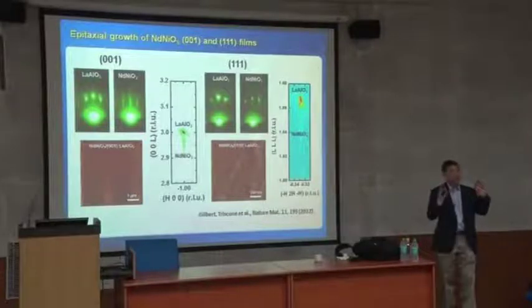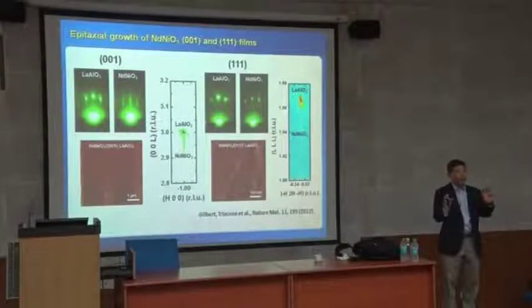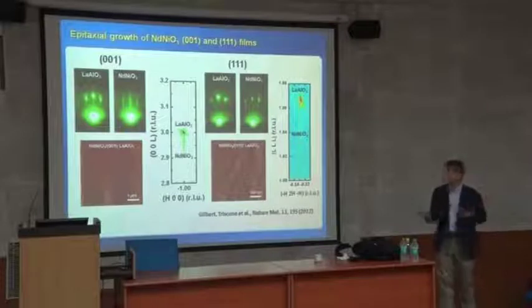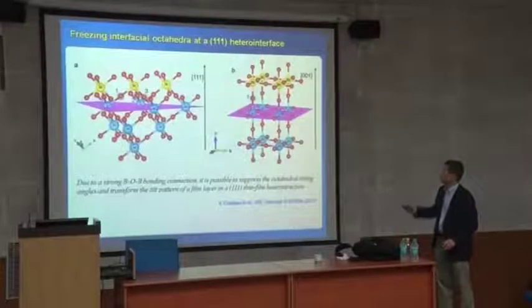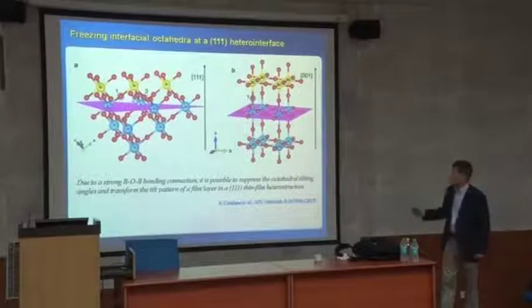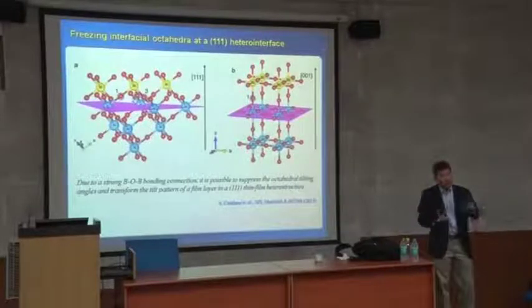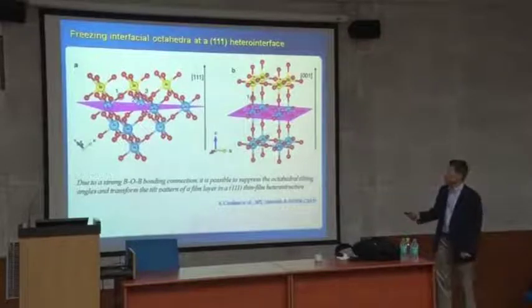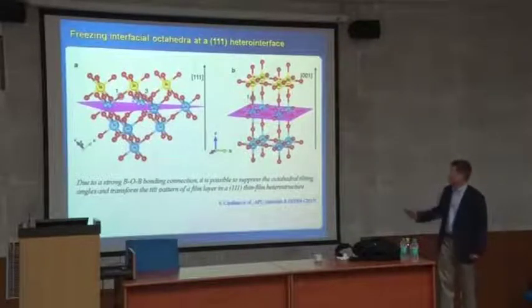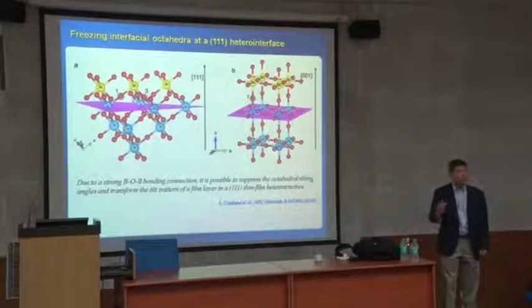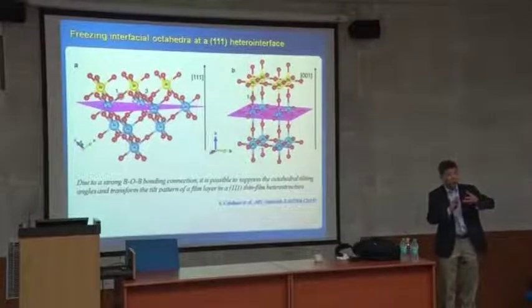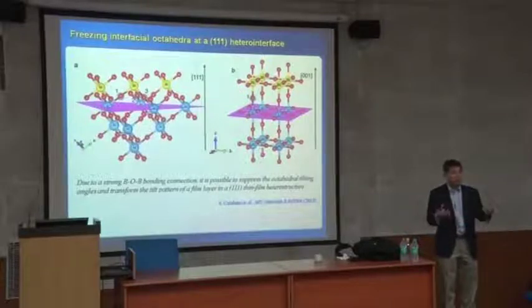111. And now you can compare 100 and 111. It really works, our hypothesis works. Our hypothesis is based on this idea. This 100 has not very effective rotation, while 111 is much more effective. So that means maybe in 100 we grow the same material, or in the 100 direction, there's no effect, which means it should be non-polar. But this one has a very strong suppression of rotation, then you will see polar.